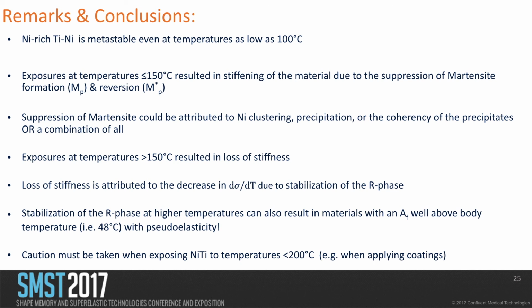Do you expect this to be a trend that continues? I stopped my presentation at 100 degrees C, but I did run some, and I'm still running some samples at 70 degrees, about a sterilization temperature, 60, 70, and it's now about maybe 4 or 5 months in, and we don't see much of a difference yet. So I think the kinetics are so slow at that temperature that, yes, eventually it's going to change, but maybe in a million years or so.